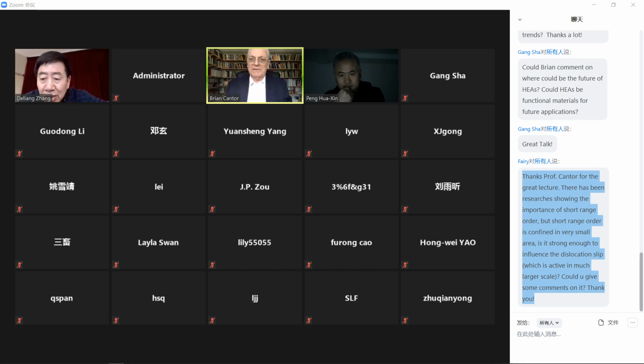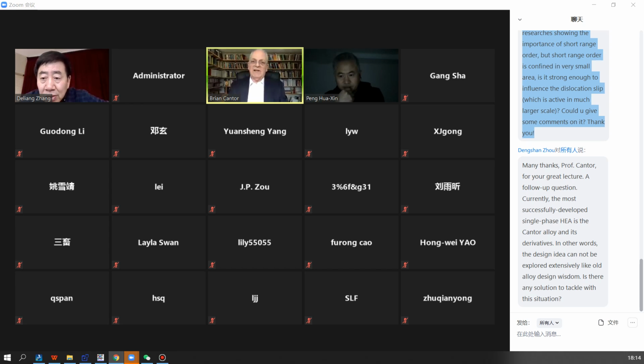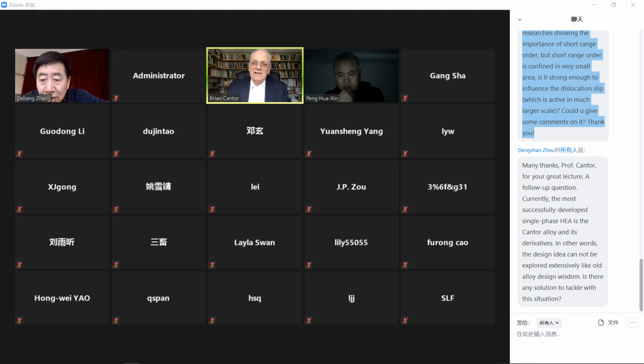Yeah, good question. It seems like it might not have an effect, but the answer is it does have an effect, because a dislocation has to slip all along its length. It's no good if it just slips one little bit of it, because then that bit gets pulled back by the rest not moving. So the truth is that the local regions affect the dislocation all the way along differently. It's one of these things where local things can sometimes have a very big effect.